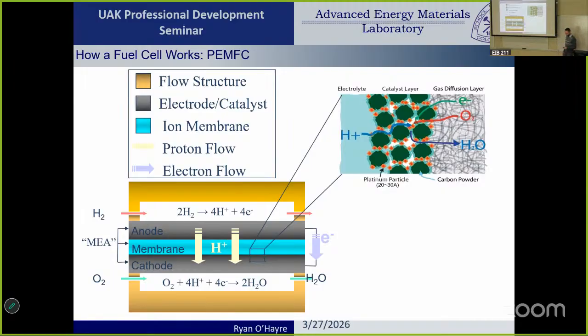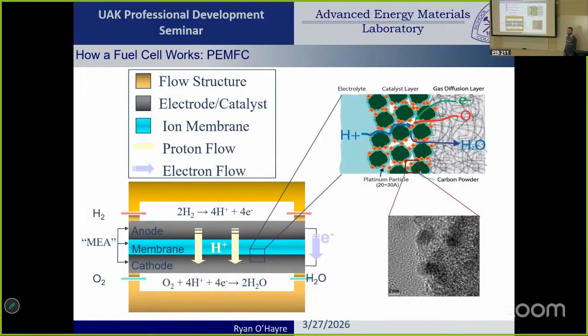Great question. Another question, so I assume the efficiency degrades over time, and if so, does it have to do with those platinum particles? That's one of the big sources of loss over time. Some of those platinum particles will move around, they'll get dislodged. You have coarsening, where the platinum particles will actually coarsen. So you have fewer of them, but they're bigger. So you're losing effective surface area. How much time? It depends, so the very best fuel cells, we'll talk about this a little bit later when we get to applications. The very best fuel cells today can go 10,000 hours, 20,000 hours. But if you're running it constantly, that only gets you maybe 2 years, right? So that's a big Achilles heel right now, and one of the major things we need to do to improve fuel cells is make them run longer.